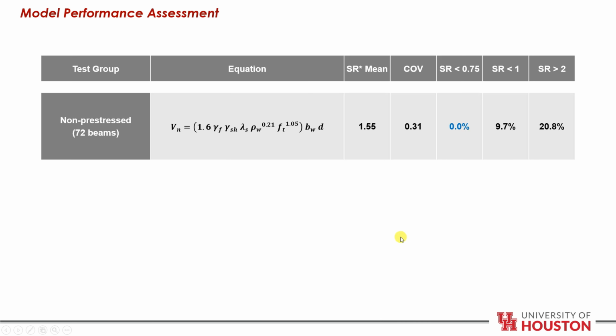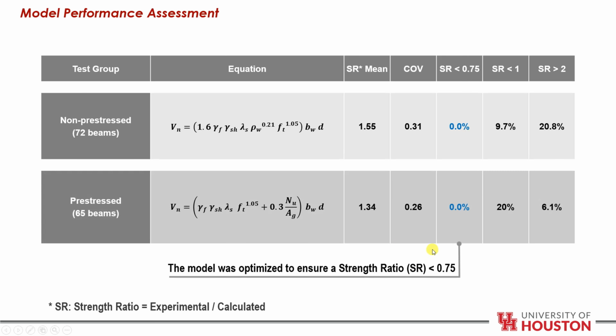The performance of the proposed equations is summarized in this table, where we can see no strength ratio falls below 0.75, where the model was optimized to ensure strength ratio not below 0.75.